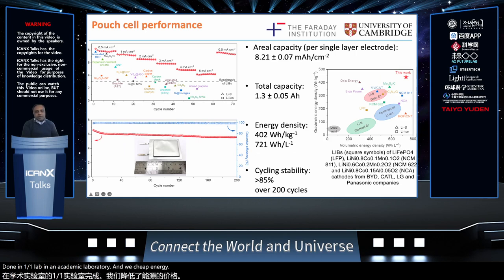And we achieved energy density that's above 400 watt hour per kilogram, and volumetric energy density that's above 700. I should explicitly point out that these values take into account the entire weight of the pouch cell, housing, everything. The only thing it doesn't take into account is the weight of these tabs, which is relatively small. And if we look at the areal capacity at different current densities, we see that these pouch cells with our 1T phase MoS2 compare favorably with other reports in the literature.